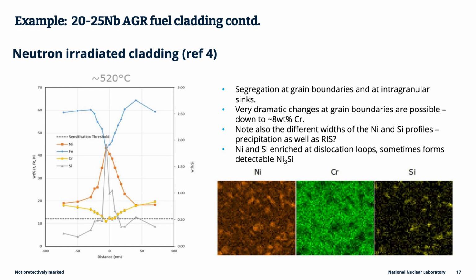And this is our LaB6 microscope, so the count rates are rather less than they were in the FEG that Chiara had been using, but we can still see the fluctuations in the concentration of nickel and chromium and silicon there. And we've got a really very good measurement of the depletion and enrichment profiles here, because these were taken using single point analyses where each of these was maybe 30 seconds of data acquisition time. So the error bars are much smaller.